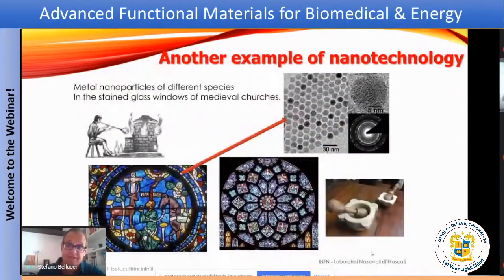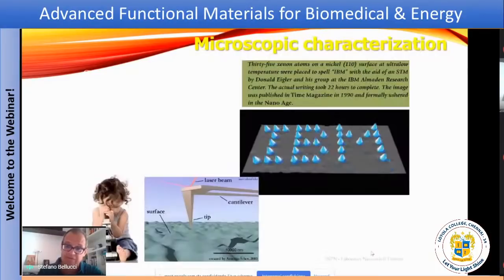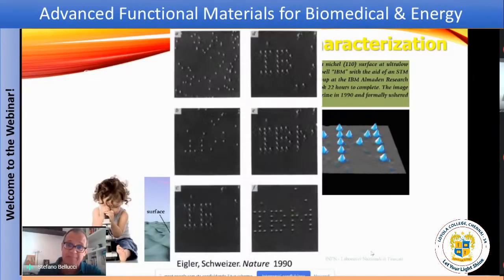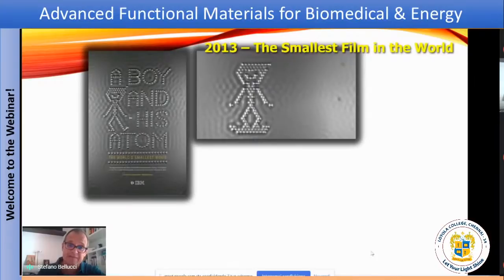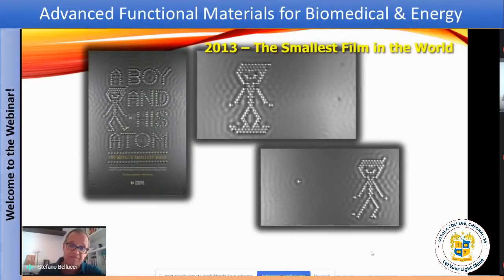Another example is provided by medieval churches where metallic nanoparticles were included in the windows, in the glass-stained windows. And you can see the method of preparation of nanoparticles in this case was typically top-down. They were crushing metals, powders, until they got into the nano size. We need to characterize these nanoparticles, and nowadays we are able to do that by different methods. Here you see an example of use of an STM, a scanning tunneling microscope, that was realized in 1990 at IBM. There's even a curious fact, 2013, the smallest film in the world was realized using atoms and allowing them to self-assemble on a surface of silicon.